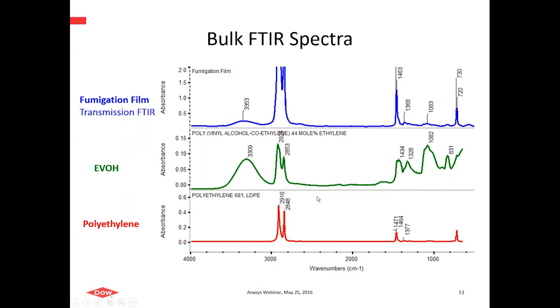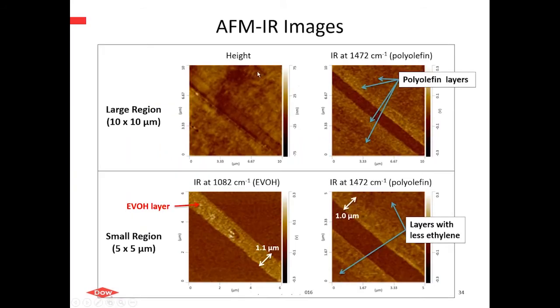And so now we know ahead of time that we can go after, let's say, unique spectral features in the mapping that might correspond to EVOH. We can look, for instance, at the OH stretch, or maybe ether type of responses down here relative to CH2 modes associated with a polyethylene. And so here's what we find with the AFM-IR.